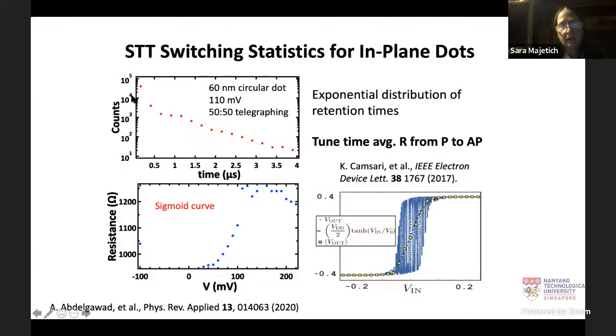And we can get an idea of what our time resolution is by looking at the number of counts. If we're looking at the number of dwell times that are 500 nanoseconds, 1 microsecond, et cetera, we see that for most of this decay, we're getting Arrhenius law behavior. So we see this exponential decay. If we go down to about 200 nanoseconds or below, we're seeing deviations because of how we're binning, but that really has to do with the electronics that we're using.